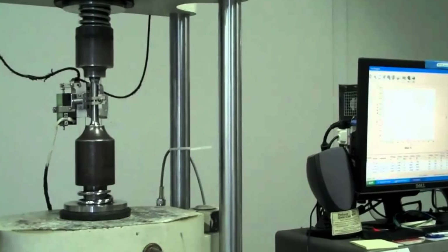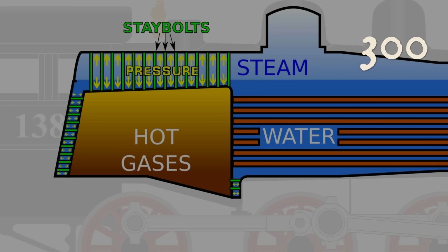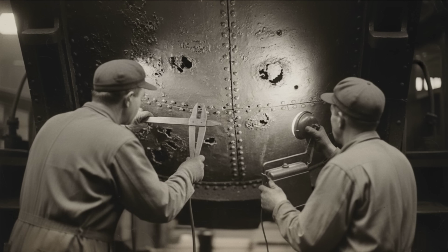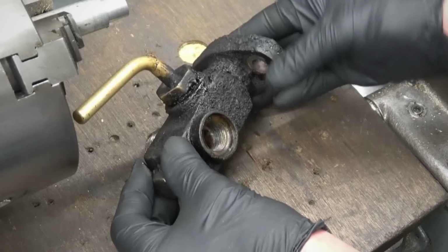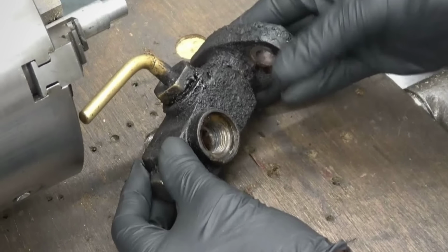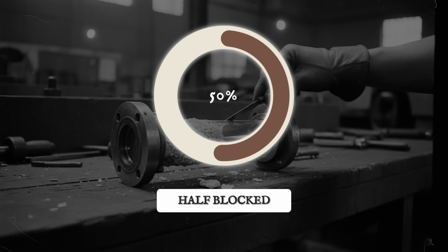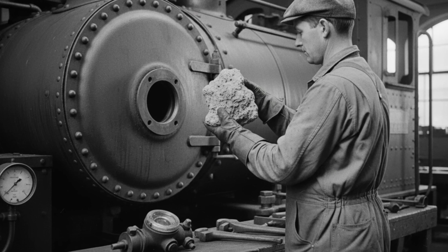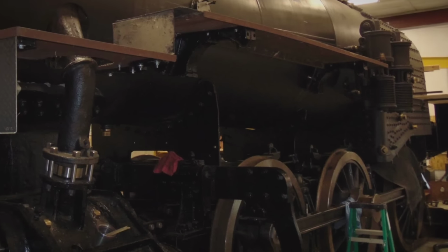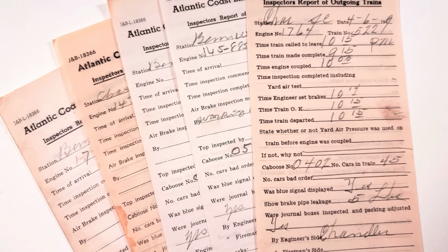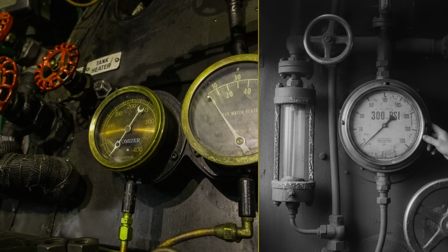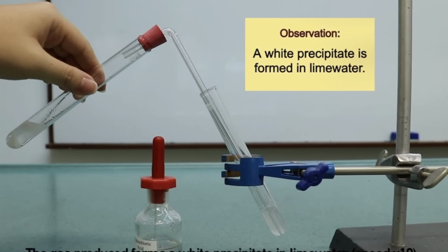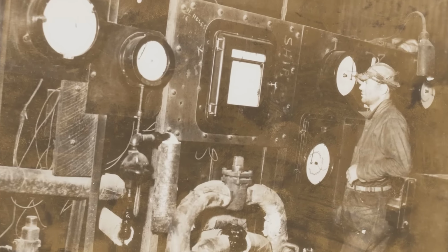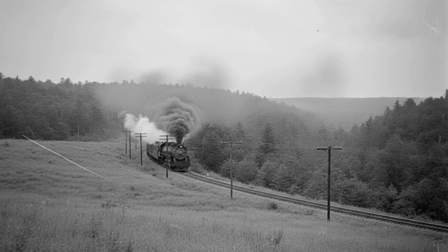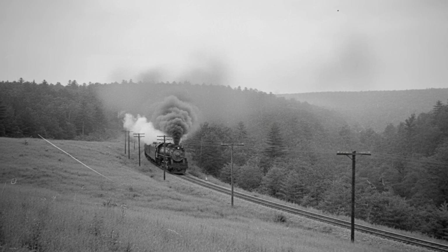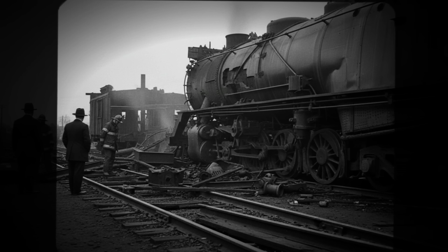Tensile strength fell away. The stay bolts, designed to anchor the firebox against 300 pounds per square inch, met metal that had turned soft and plastic. Investigators later scraped the glass and found a crust of calcium thick enough to block half the bore. One inspector described it as a stone plug, not a sight glass. The root cause was not a broken part, but routine cleaning skipped in the name of schedule. In an engine where every pound of pressure is a loaded weapon, that omission handed control back to the laws of chemistry. The result was a false level, a silent countdown, and a 600-ton locomotive pushed past its threshold by nothing more than a dirty indicator.